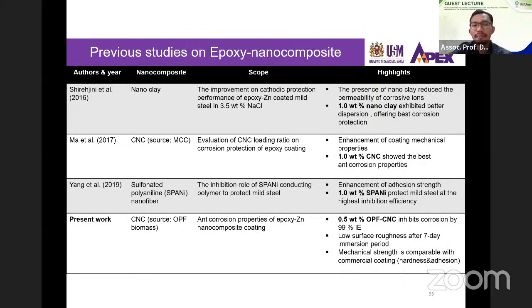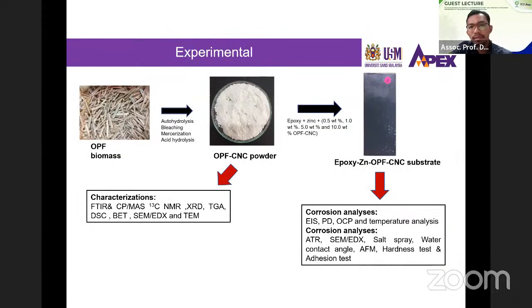The application of cellulose as filler in coatings has been done by several authors. But what we want to do is blend the cellulose nano that we have obtained together with the epoxy coatings, and after that it will be coated onto the metal surface. So this is what happened. After we isolated the CNC from OPF, we blended it together with epoxy plus zinc, and we coated it on the metal surface, and we further tested it for anti-corrosion testing as well as surface analysis.